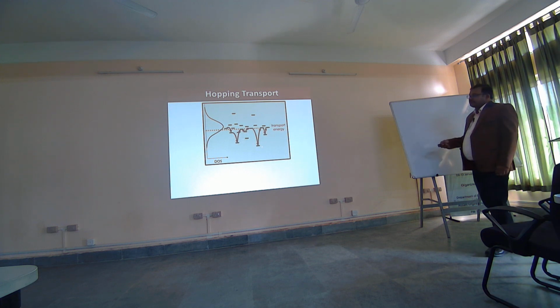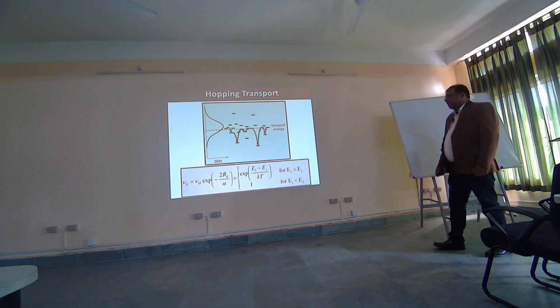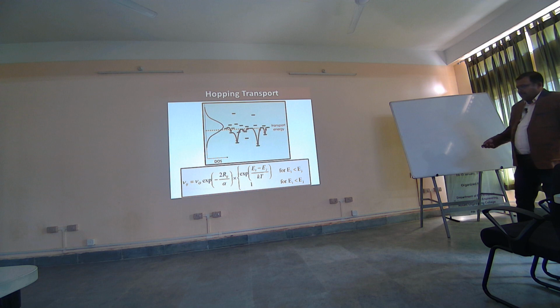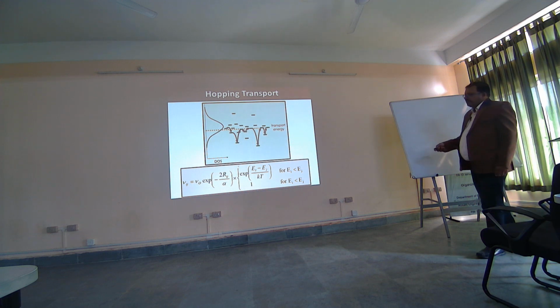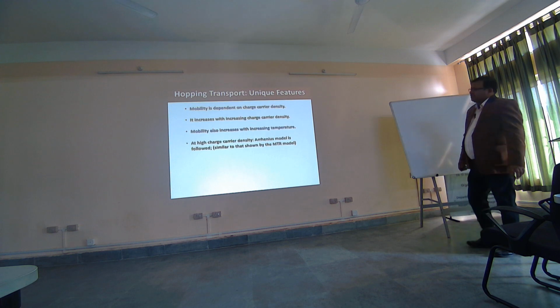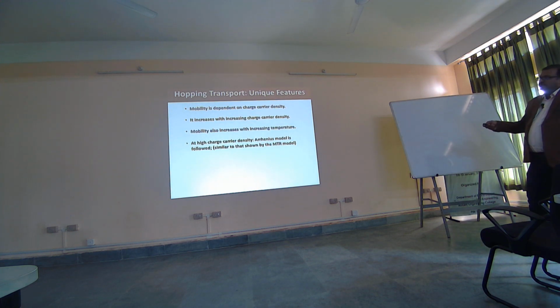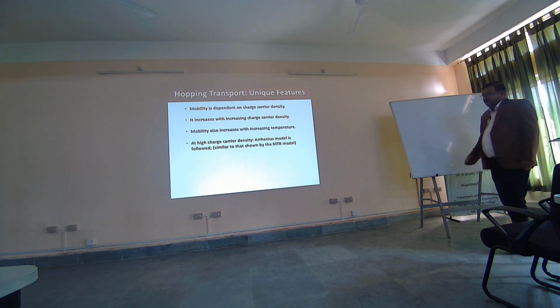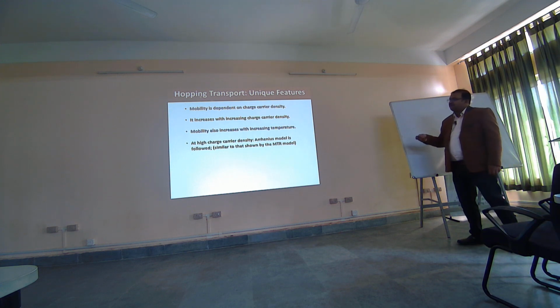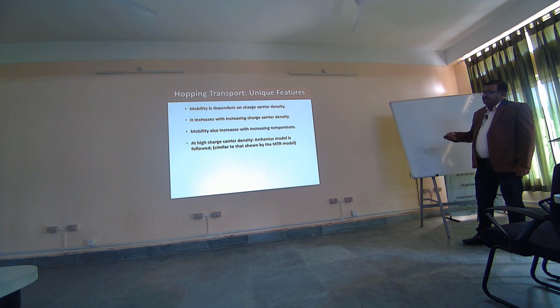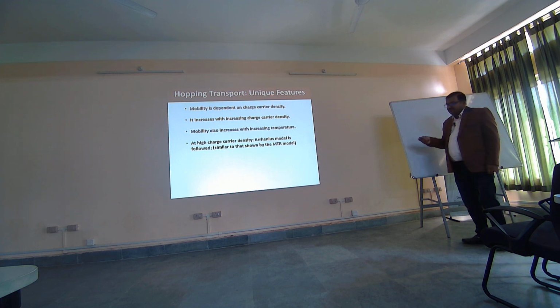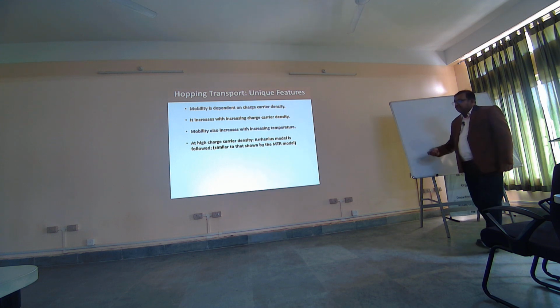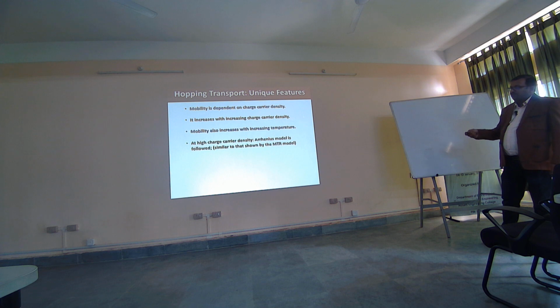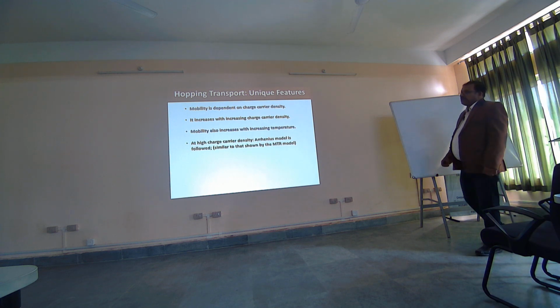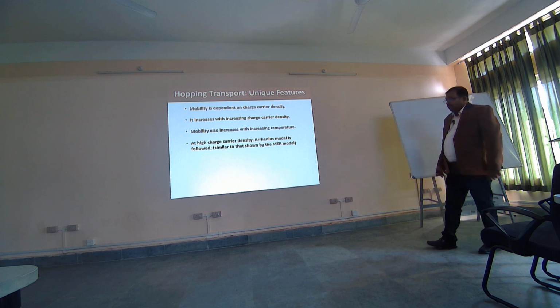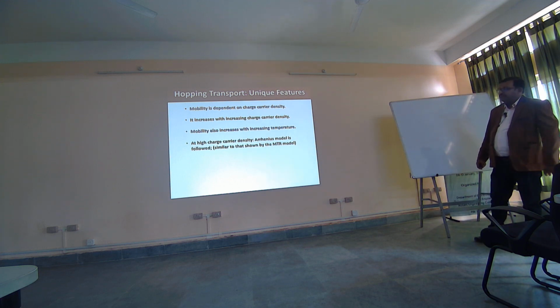So typically this is what is referred to as a hopping kind of charge carrier transport, and this is the empirical relationship between a charge carrier hopping from the ith to the jth energy level. Anyway, so basically hopping transport is one of the unique features of organic semiconductors, and in this kind of transport, mobility is dependent on charge carrier density, and it increases with increasing charge carrier density, and it also increases with increasing temperature. So these two attributes are very unique and clearly distinguish between what is hopping based charge transport and what is a band type charge transport.